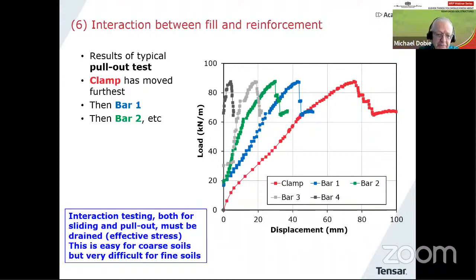So let me just go to this blue point, is that when we do interaction testing, whether it's pull-out or sliding, it needs to be an effective stress test. It needs to be a drained test. If you remember the discussion earlier on about effective stress design. Now that's easy for coarse soils, for gravels and sands, no problem at all. But it's very difficult for fine soils. It's my experience that in the literature, there are very few published results of genuine effective stress interaction tests. Simply because if you have a large shear box and you put a clay fill into it, it takes a very, very long time to shear if you want to make sure it's an effective stress result.